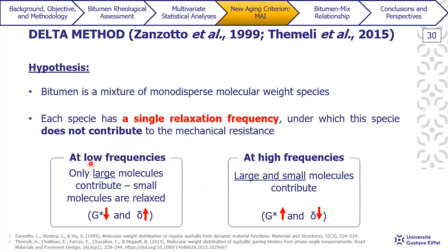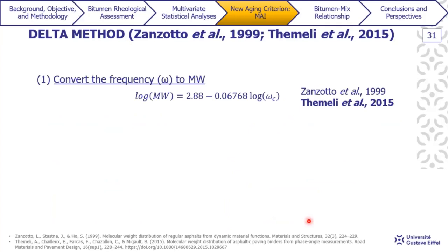At low frequencies, we have only large molecules contributing to bitumen's mechanical behavior, whereas small molecules are relaxed, which causes the modulus to decrease and the phase angle to increase. And on the other hand, we have a situation at high frequencies where not only large, but also small molecules will contribute to the global mechanical behavior, which will cause our modulus to increase and our phase angle to decrease. So the first step of the delta method is to convert our frequency to molecular weight. And in this case, we use this equation that was first proposed by Zanzotto and then was also corrected by Themeli.